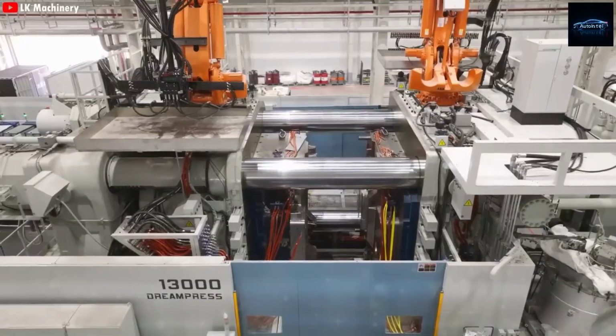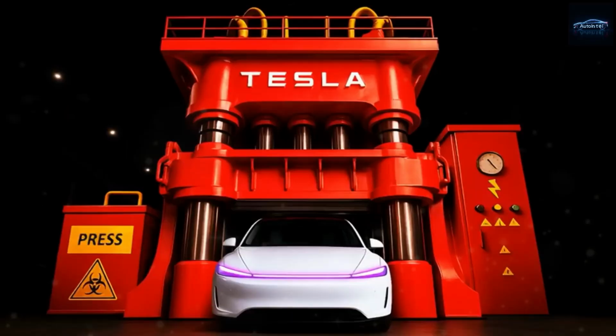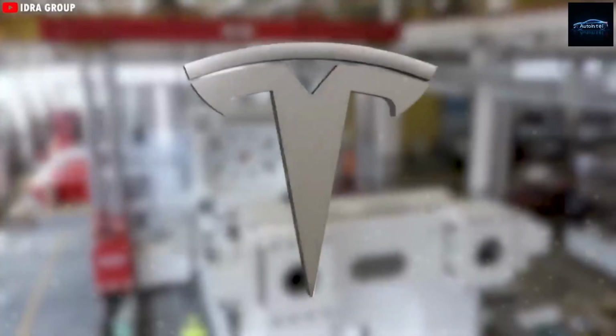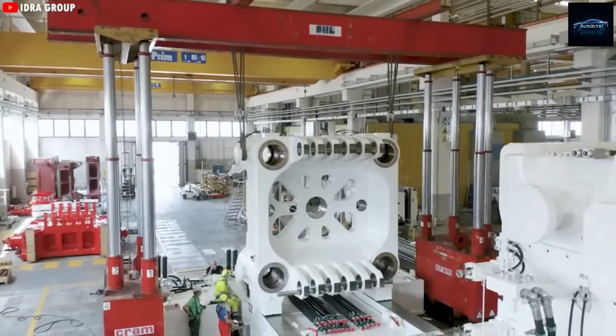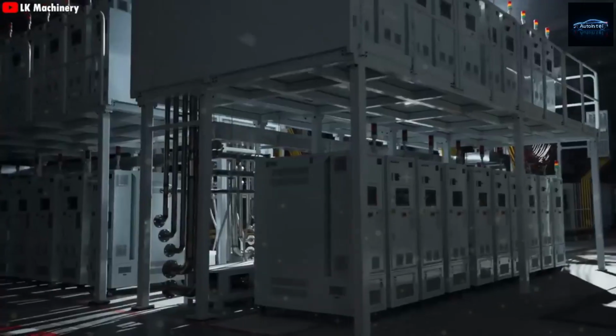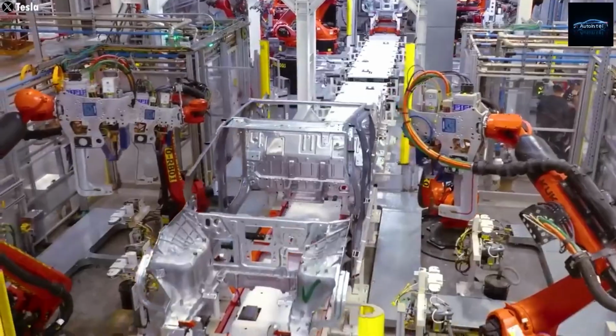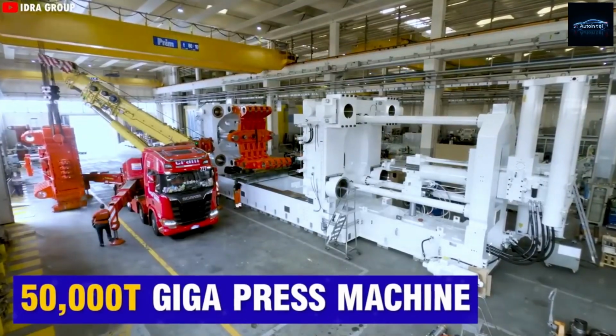One furnace acts as the melting furnace, powered by natural gas and operating at around 1,562 Fahrenheit. The other serves as a holding furnace, electrically heated and maintaining a temperature between 1,382 and 1,562 Fahrenheit. As previously mentioned, inside the holding furnace where the molten aluminum is stored, the empty space is filled with nitrogen gas. This is no coincidence. Nitrogen acts as an invisible protective layer, preventing the aluminum from coming into contact with outside air and thus avoiding oxidation. At the same time, it helps maintain a stable temperature, keeping the metal in a ready-to-cast state.